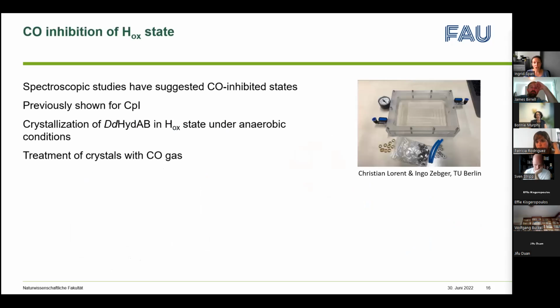And the next step that we looked at is the CO inhibition. So spectroscopic studies have suggested that the hydrogenase can form CO inhibited states. And this was previously also shown for CpI. And we tried to crystallize the HOX state this time. It also crystallized very beautifully in the glove box. And Christian lent us this nice chamber where we can put our crystal tray in and then expose it to CO gas.